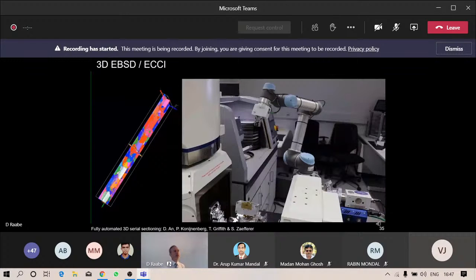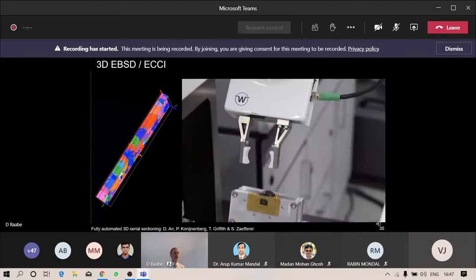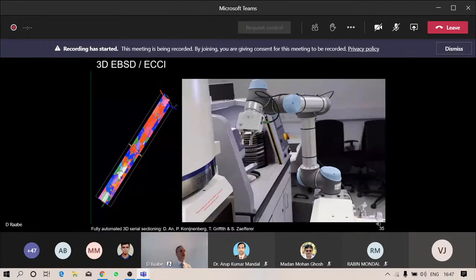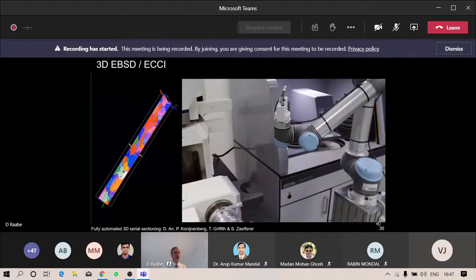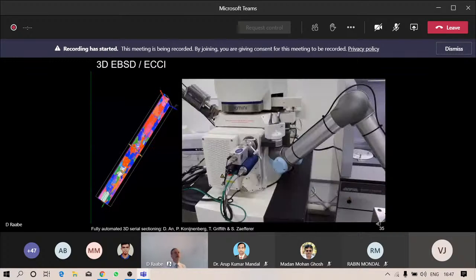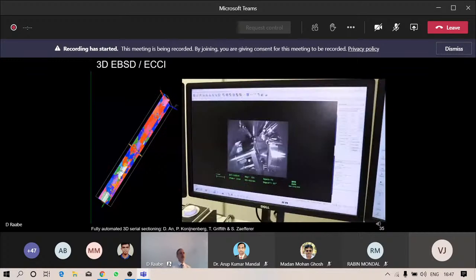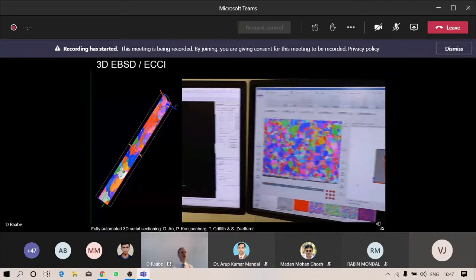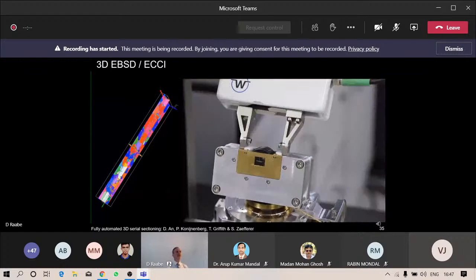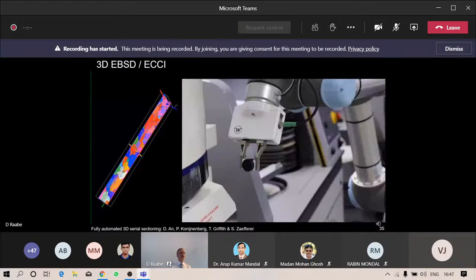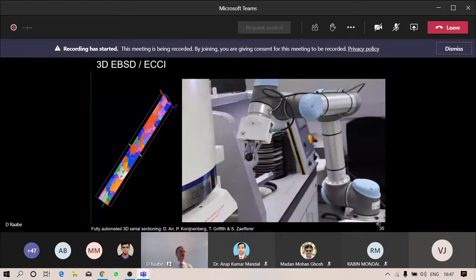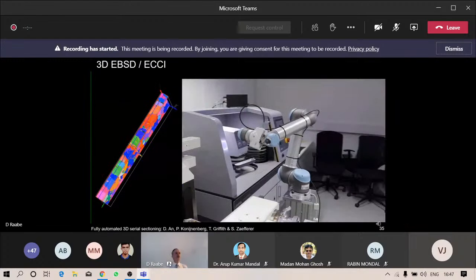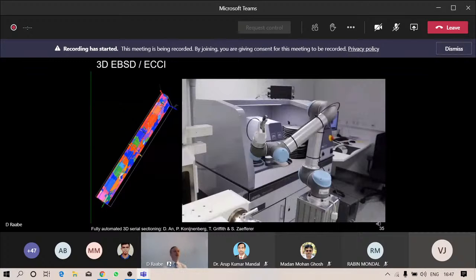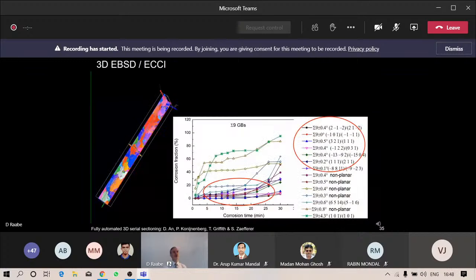We connected the robot to a Zeiss Gemini microscope, for high resolution field emission measurements of ECCI contrast, of EBSD contrast, and so on. And you see how the robot is alone operating this and starting to do the measurements, getting you the microstructure results you want. Then the robot stops the experiment, takes the sample out, and runs the next polishing round. And you can, of course, define the thickness that you have removed between the subsequent serial sectioning polishing steps, and can get all kinds of microstructure 3D information, such as a corrosion fraction as a function of corrosion time for different grain boundaries and so on, like here from a stainless steel.